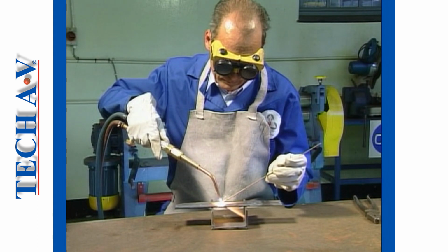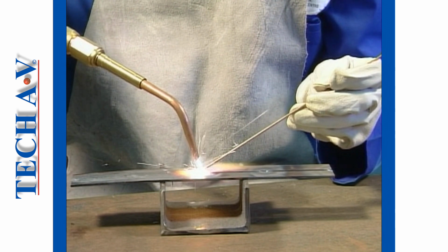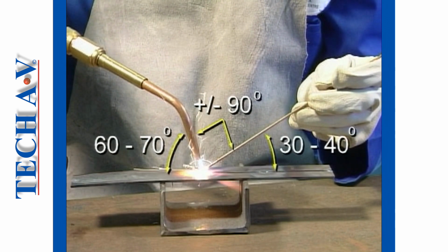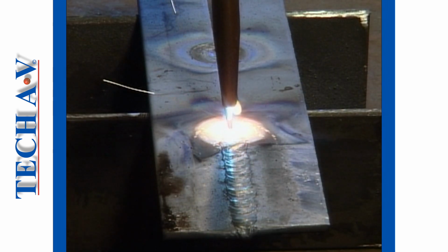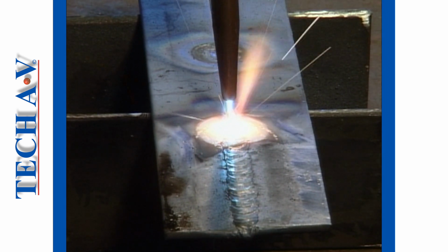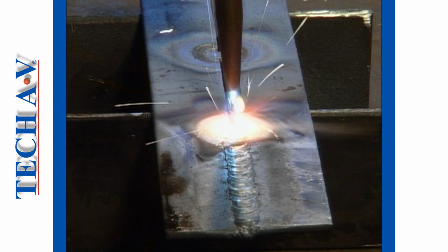If we examine a skilled welder in action, we can observe all the elements that we have covered. First, we see that the torch angle and the filler rod angle make an approximate right angle. We see the cone of the welding flame being maintained at the proper distance of 4 to 5 millimeters above the work surface. We see that the torch is constantly weaving to keep an even distribution of heat across the joint. The filler rod is being introduced into the molten pool, making sure that the fill is constant and even.